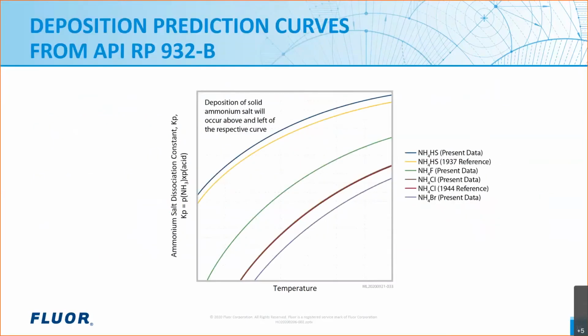So here are the deposition curves. They're from API 932B. We redrew them. The x-axis is temperature. The y-axis is a product of the partial pressure of ammonia times the partial pressure of the acid species, the chlorides, the bisulfide, and it even has curves for fluorides and bromides. This allows you to see, for a given unit, say 3 ppm of chlorides and then the ammonia, where the ammonium chloride deposition temperature would be.